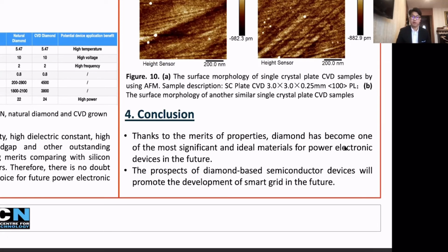sample and the boron-doped diamond sample are high quality samples. With a deep research in AFM and Raman spectrum of diamond, it will largely improve the quality of preparation of diamond, which will help to reach the requirement of higher quality application. For example, the single crystal diamond could widely be used in the semiconductor devices and the particle detector, even in optics applications. And for the polycrystalline diamond, although there are some grain boundaries in the surface, it is still possible to apply in the cutting tools and wear-proof tools.